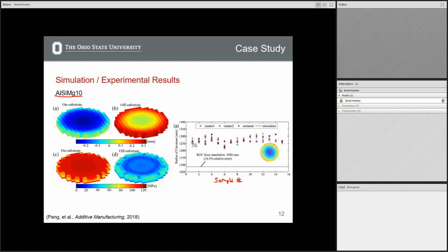This is then the actual radius of curvature that we got from these parts. This constitutes about a 16.5% relative error, which is fairly reasonable for how simple our models were. But we're getting in the ballpark in terms of understanding what this distortion is.